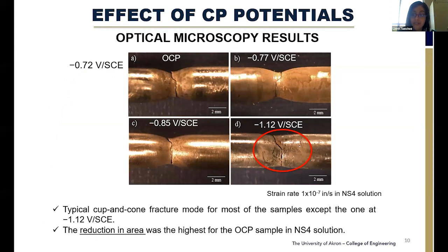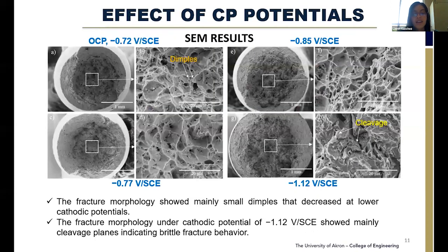So after we analyze the fracture mode, we now analyze the fracture morphology, that is the tip of the sample. And in the SEM results that I show here, you can see how mainly at OCP, the sample shows mainly dimples or microvoids, typical of ductile fracture. However, the fracture morphology changed when we go to more negative cathodic potential again. That indicates a brittle fracture behavior in the sample, as we see here, the cleavage planes at 20 microns. So when we have more negative cathodic potentials, we have more susceptibility.